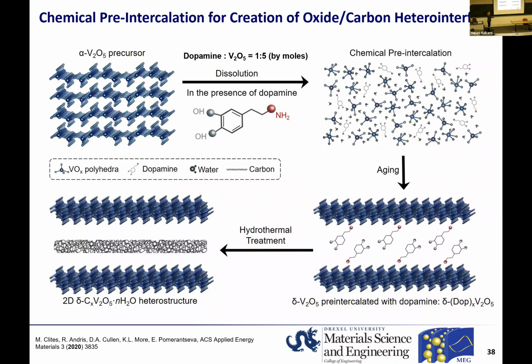So through exactly the same synthesis process, we were able to chemically pre-intercalate these dopamine molecules into the structure of bilayered vanadium oxide. And remember, we cannot use high temperature, so we cannot anneal the sample at 400 C, because the bilayered structure will transform into something else. So we are limited by temperature.